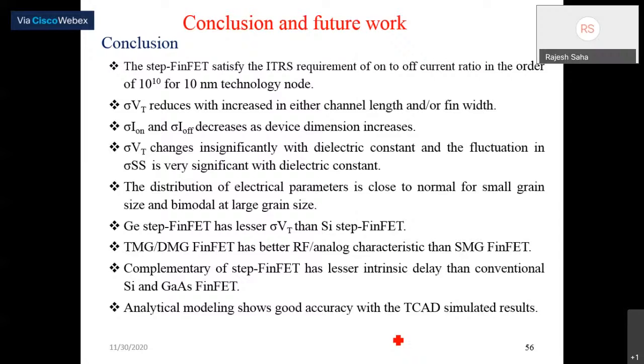Also we reported on the germanium-based step FinFET, and we have made a comparative study in terms of work function variability of the electrical parameters. It is seen that the germanium device shows lesser sigma VT than the silicon step FinFET. And the dual and the triple material gate FinFET have better RF and analog characteristics than the single material gate FinFET, as you have observed.